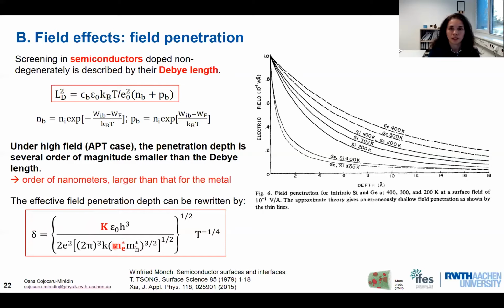Then we have also the effective mass of the electrons. Of course, if we have wide band gap materials, we have a very big difference, or a very low probability of an overlap between the minimum of the conduction band and the maximum of the valence band. So in this case, the effective mass of the electrons would be simply the same as the constant mass of the electrons that we know. But for narrow band gap materials, the effective mass of the electron will be very different from the mass of the electron. So here it's also very important to pay particular attention to this parameter.